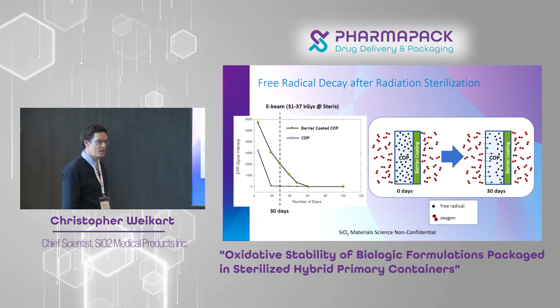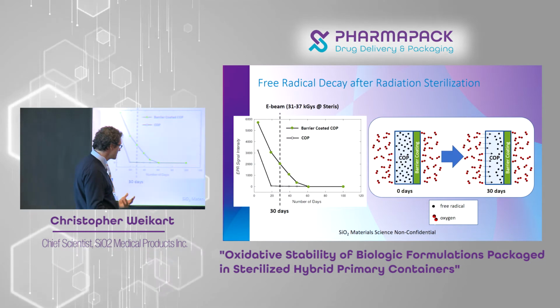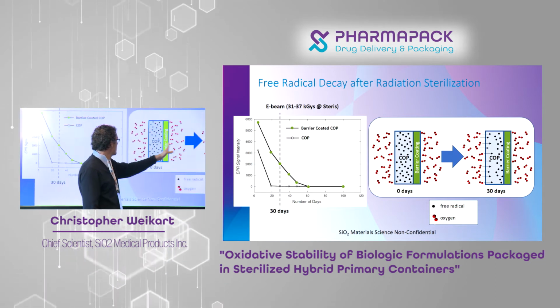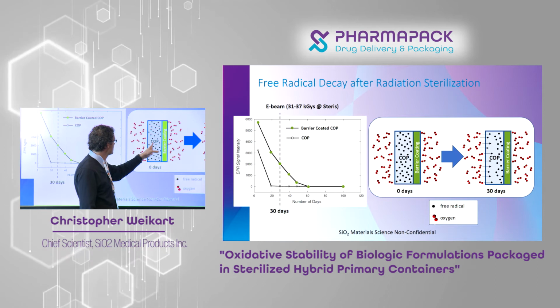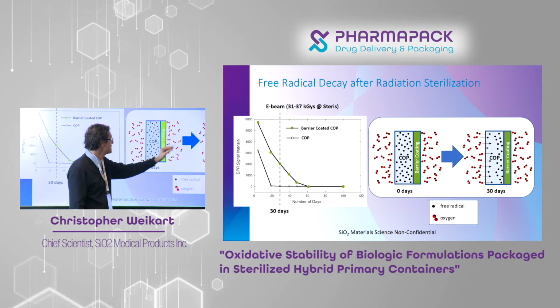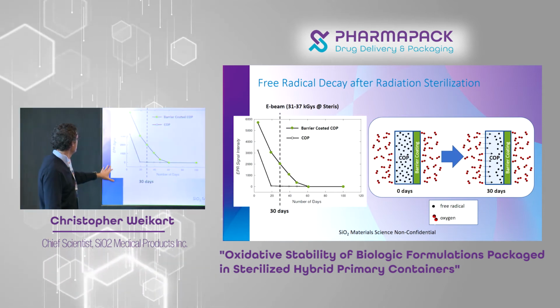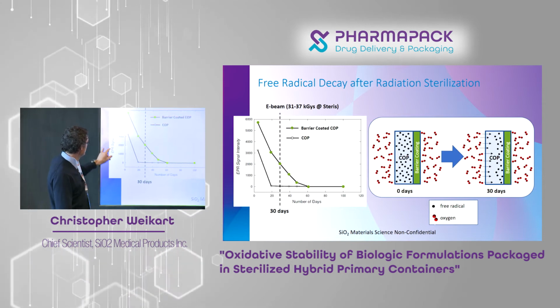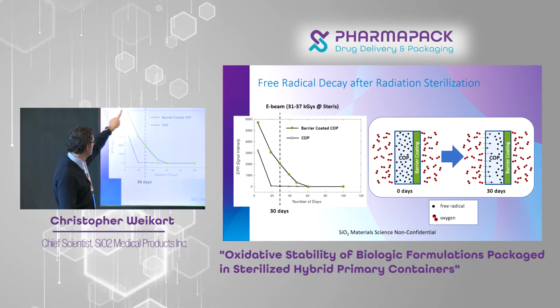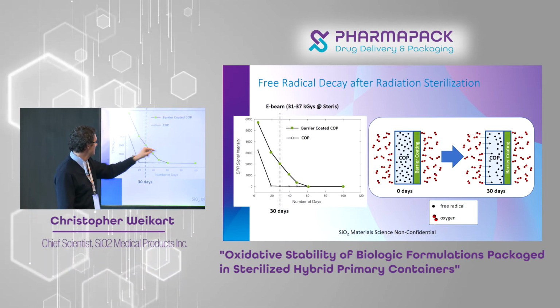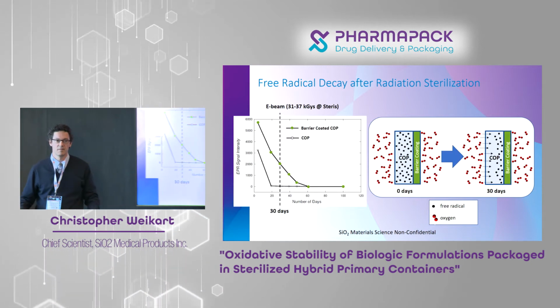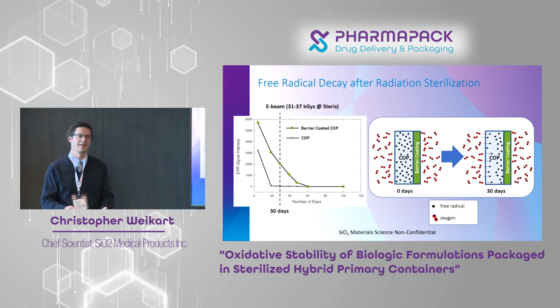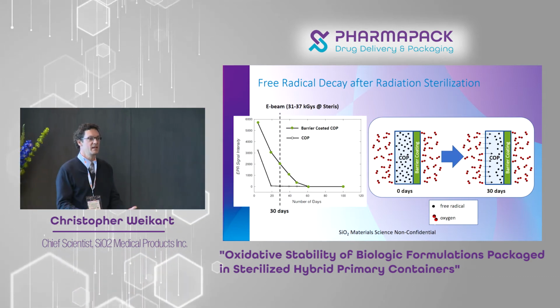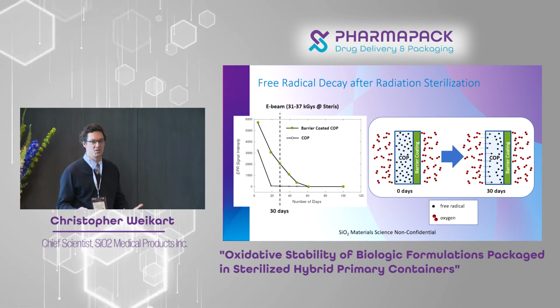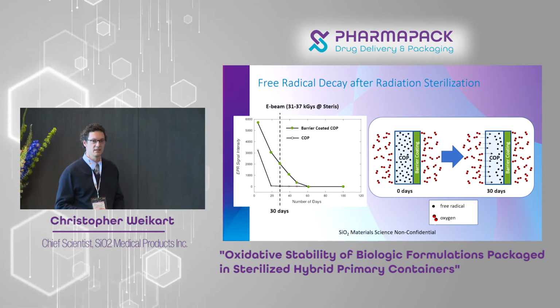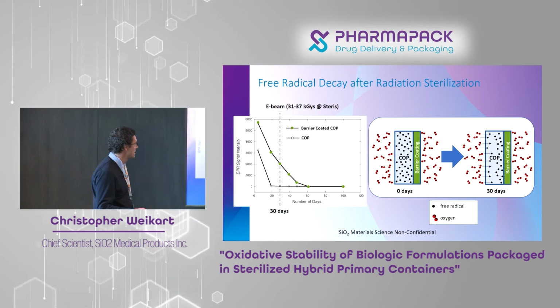So what happens when you have a coating? Well, the coating's a barrier, so it doesn't allow oxygen to come through the barrier coating into the polymer to scavenge these radicals. You only have oxygen coming in from one side. And we've actually been looking at the number of free radicals in the polymer itself, and you can see the difference in the decay rate because of the barrier coating. And why is that important? Because when you then put the drug product in, you're preventing any of those oxidative species getting into the package and oxidizing the drug. And I'll show you some data a little bit later on how we actually accomplish that.